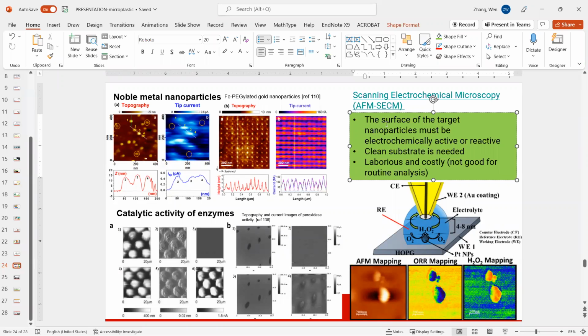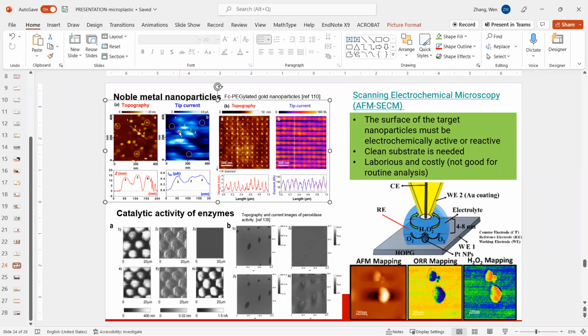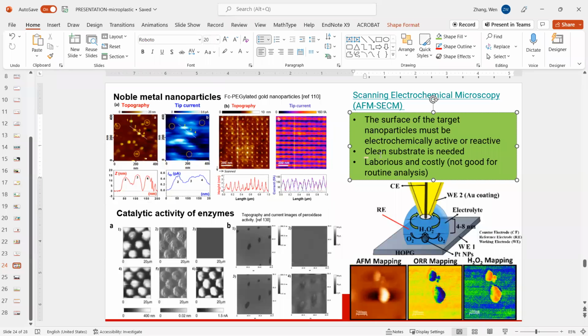That's also doable, right? So for example, if your sample matrix is very reactive, you can generate pretty high currents. I think this is the example here. On the opposite side, you can have pretty high currents on your matrix, on your substrate surface, but once your tip engages with your sample, you have a limited or reduced tip current. That's the opposite method to identify the nanoplastic particles. I think that's also feasible.